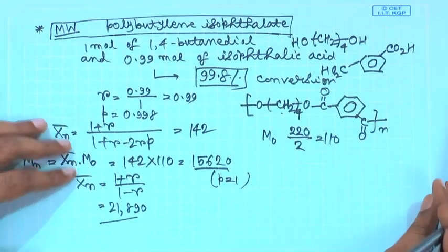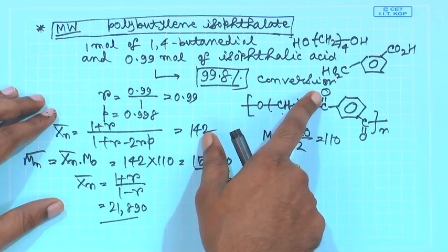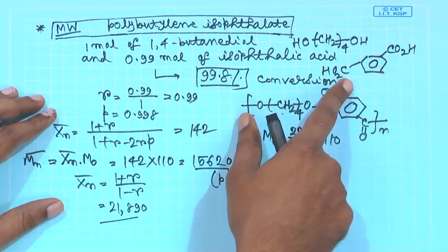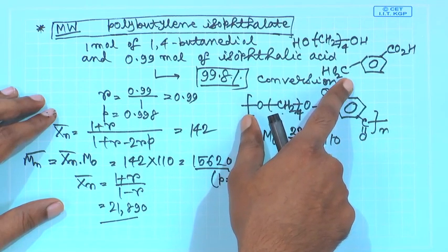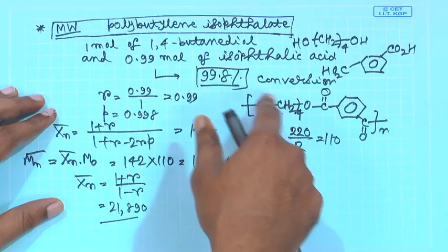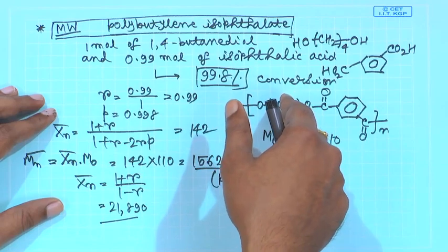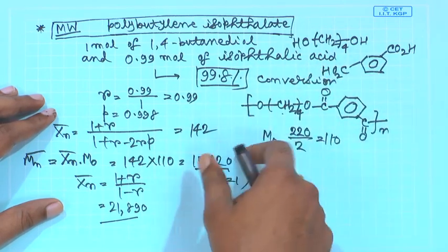So, this is something you can control to start with, and then you can find out the conversion, because from how much concentration of carboxylic acid is remaining, you can find out the conversion. The concentration m is equal to m0, the initial concentration, minus m0 into p, where p is the conversion, and that will be equal to your final concentration, which you can find out.